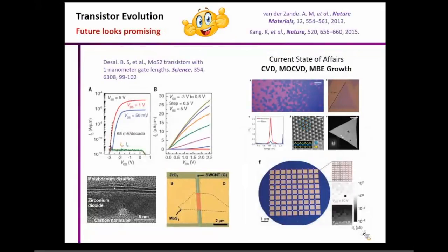And to be honest, the future looks very promising, because very recently a group from Berkeley, Ali Javey's group, actually demonstrated a transistor with a gate length of only 1 nanometer. Okay, this has been already demonstrated, where they are using an MoS2 flake and they are gating it by a carbon nanotube. The carbon nanotube has a diameter of only 1 nanometer. It is a metallic carbon nanotube that can act as a gate.